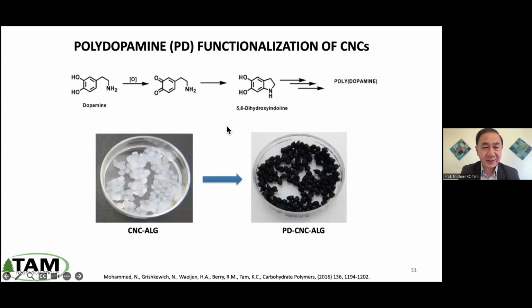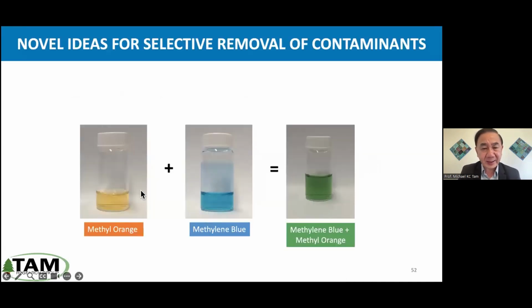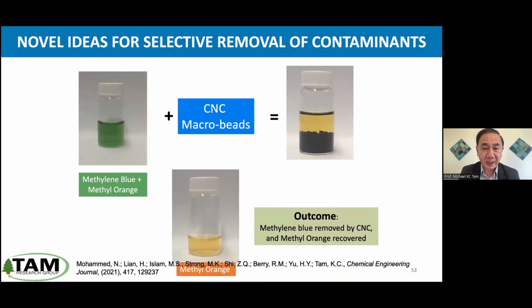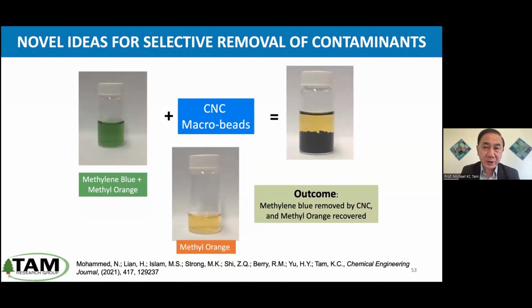Then you can do chemistry to the system. Very simply, we coat it with dopamine, and now we have dopamine that has specific affinity to the methylene blue. So we take this demonstration, we mix methyl orange and methylene blue. As you know, this is physical mixing and gives you a different color, green. So if you find a material or adsorbent that can remove blue dyes, then you can restore this solution to have the yellow or orange solution. So we add our material to this, and you can see when you add our beads to this green dye, we remove methylene blue, and we now recover a solution that has only methyl orange. So you can imagine sequentially introducing different types of material, designed to remove specific dyes, and we can restore this system.